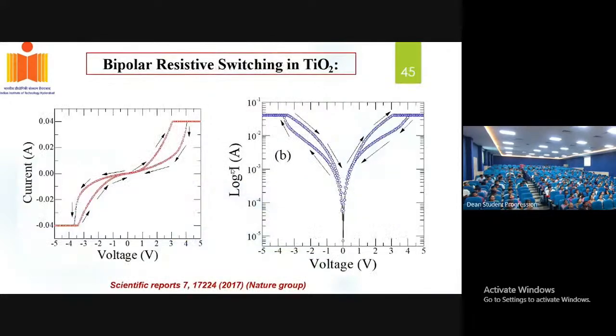These are the IV characteristics that we have obtained. We varied the voltage and measured the current. We started over here. Initially the device is at a high resistance state, and we feed the voltage. The device has gone from the high resistance state to the low resistance state, and then again from the low resistance state to the high resistance state. As we discussed in the classification of resistive switching devices, we have two classifications, unipolar switching and bipolar switching. In unipolar switching, to get the set switching and the reset switching, you need to apply one polarity of the voltage. In bipolar switching, two polarities are required.